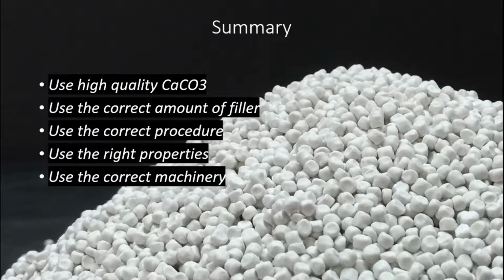So it's really important to use a high quality calcium carbonate, and within the quality comes the particle size of the calcium carbonate, which will affect the overall appearance of your film as well as your processing. Secondly, we have noticed that using the correct amount of the filler is also really important, because the more filler you use, the lower the properties or appearance of your end product, especially the films, will be. Using the correct procedure is really important while manufacturing the calcium carbonate filled master batches. As we have seen, if the procedure is not correct, and if you're not using the right parameters, we will be getting problems during the processing and in your end product.